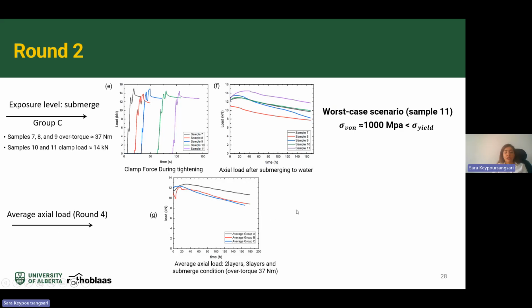In order to compare the results in round 2, we took the average of group A, B, and C. And you can see how this axial load is different in group A, B, and C. But in all groups, they follow a similar trend. First, the load starts increasing until it reaches the peak, and after that, it decreases. This is because when wood absorbs water, it expands, and this expansion starts from the edges and outer part of the glulam. So when it expands, it tries to push the steel plate to the top, and it increases the axial load on self-tapping screws.